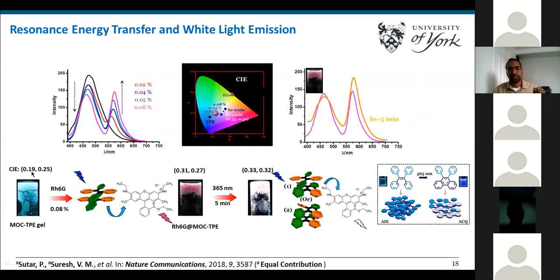It is a good idea to see the actual color of the emission on a chromaticity diagram. The CIE coordinates indicate the actual color of the emission. Here, circled in blue, is the CIE of this particular gel. We can clearly make out the emission is slightly bluish and cyanish. The corresponding emission spectrum of this gel is the black curve here, which is purely the emission from the tetraphenylethene. Now we used the energy transfer phenomenon again to obtain white light emitting gels.